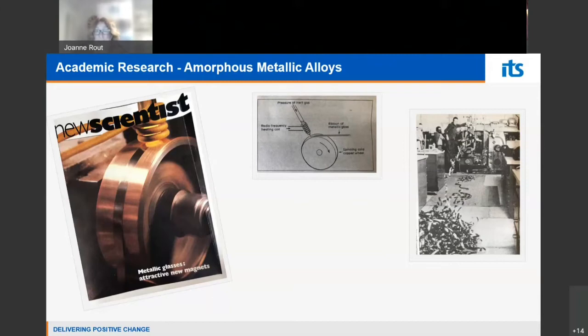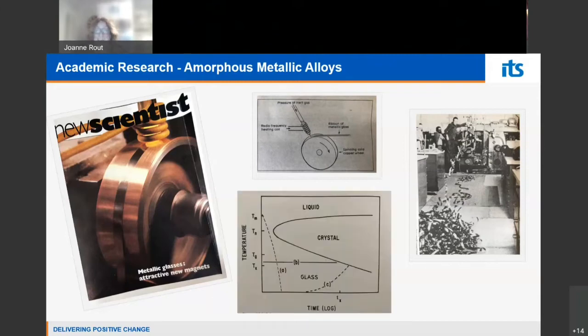So there's the time-temperature-transformation diagram. If you look at the dotted line, curve A, and note the quality of this diagram: in those days, everything was hand drawn. So that's a TTT diagram that I hand drew. Following curve A, start with the melting point, and as time goes on, you're cooling it down past the peak crystallization point, Tn, so you're avoiding crystallization. Go through Tg, the glass transition, which effectively freezes in the structure, and down to room temperature.